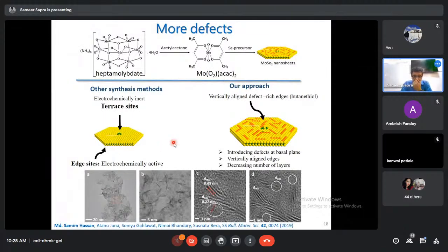And the reason for that is because if you look at these orange lines over here, as opposed to the yellow ones, these orange lines indicate vacancies of selenium atoms. And when you have vacancies of selenium, the molybdenum atom from the plane below it tends to attract the next nearest neighbor selenium atoms, and therefore that distance gets reduced and it kind of folds. And you see all these crumples, okay, in both these images. But then we've established that yes, these indeed are molybdenum selenide layers, and all these high resolution images confirm it corresponds to the D110 plane and D002 plane and so on and so forth, saying that yes, we do have molybdenum selenide. But then crumpled sheets do not fetch you much advantage, and we had a very difficult time publishing this paper.